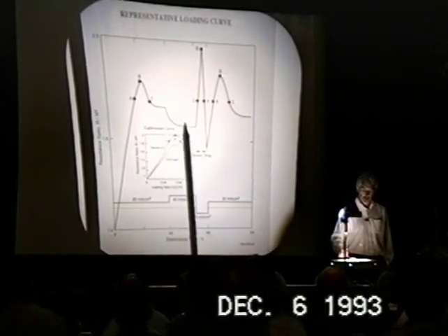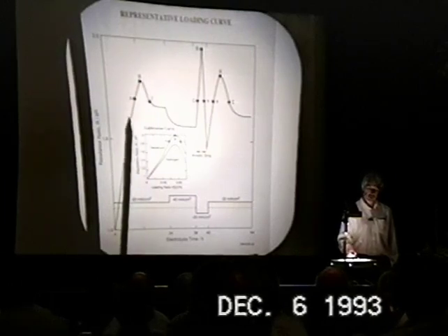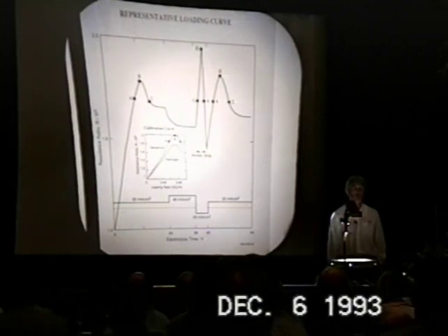The other method, though, is that we frequently strip the cathode. So you make the cathode anodic, go up through the maximum, down the other side, and then make it cathodic again. You'll traverse the maximum and go back to the right-hand side. So you'll see this sort of double-value function, which is a very good indication that you're on the right-hand side of the maximum.